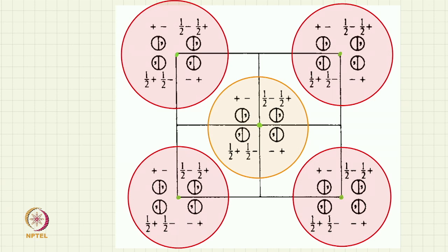So, then this completes the entire general position diagram. If you count the number of general positions within the unit cell, you can see that there are 16 general positions within the unit cell. So, I will be counting 2 here, 2, 4, 6 and 8, and there will be 8 in the center. So, there are 16. I am not counting for example these, because these are outside the unit cell. So, within the unit cell there are 16 positions.